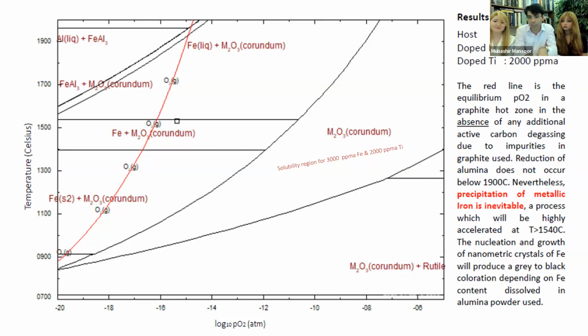We are not very much into the gemological identification world, but we share our knowledge with the gemologists as much as we can, as much as we know, of course. And that leaves some alarm bells most of the time because sure, if the material has been heat treated at a high temperature, you would know it for sure. But if it was treated at a very low temperature, in theory, it could still happen. There is nothing against it. Some people think that if you reduce the temperature to 1000 Celsius, you can never dissolve rutile in sapphire. That is not correct. You can dissolve rutile completely even at 900 Celsius. And we will show you an example by the end of this talk, which was mind-blowing for us.